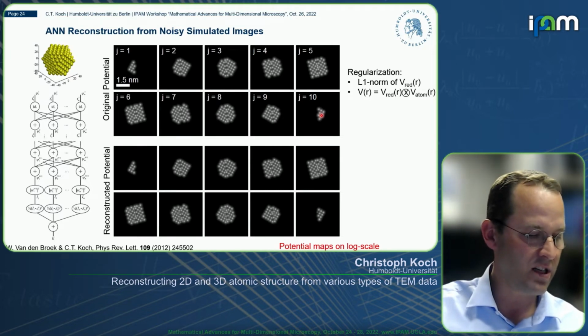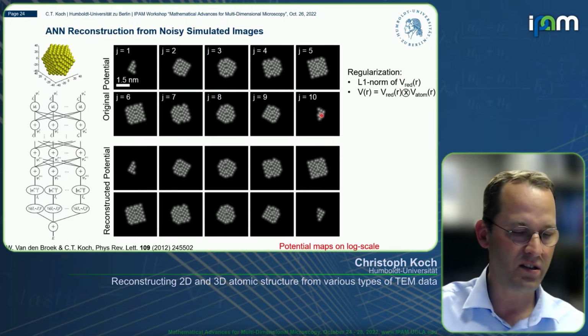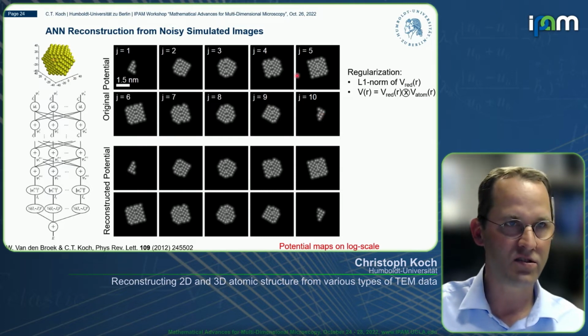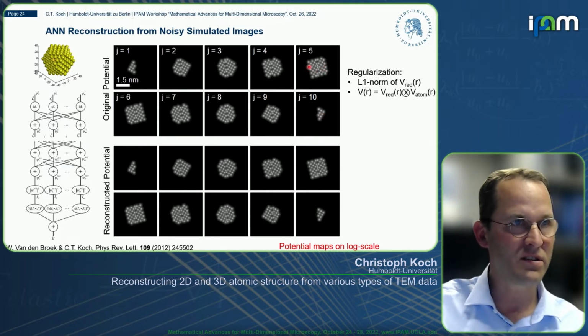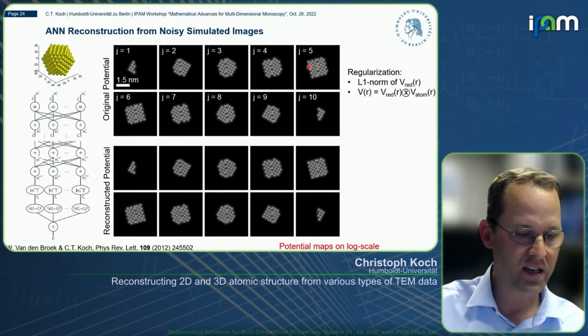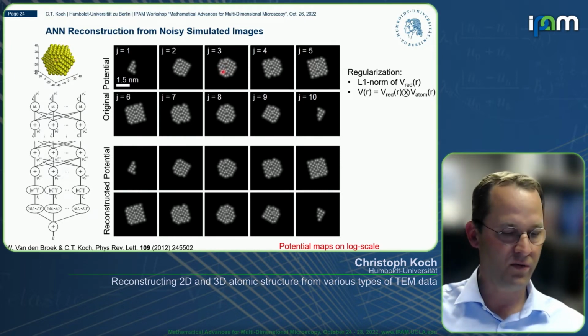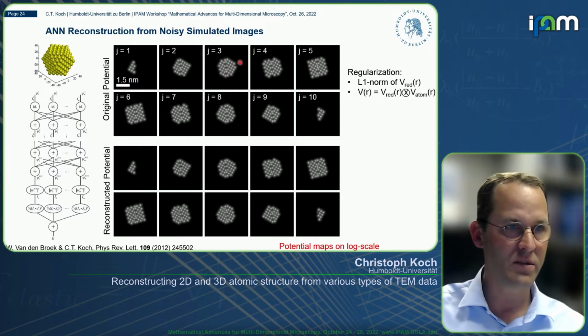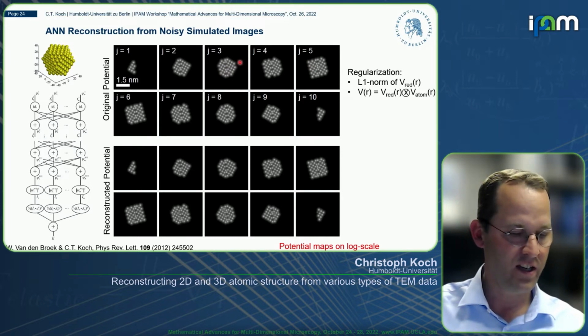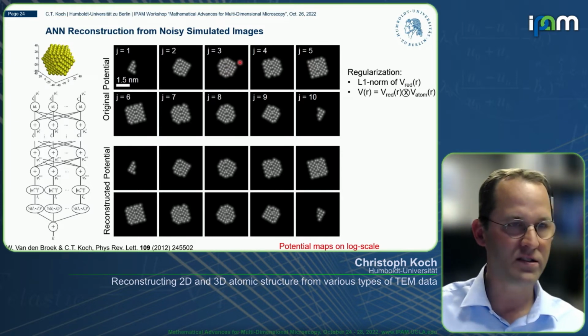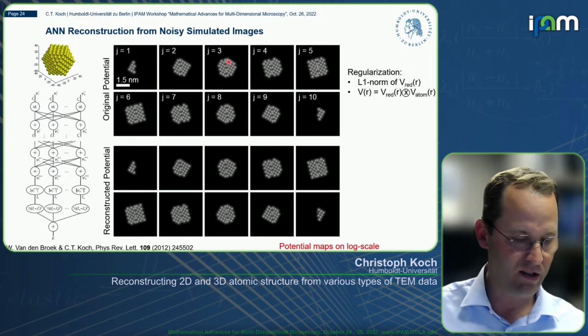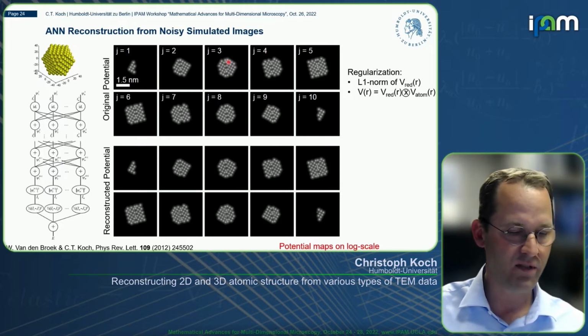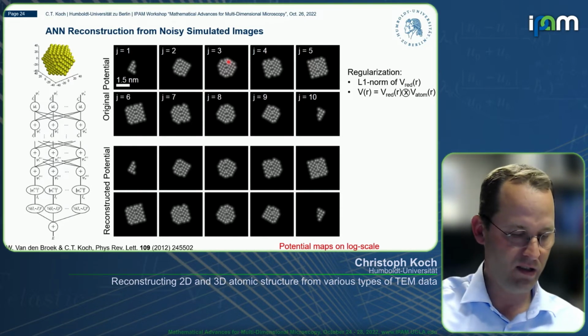And this particle here was tilted, so you can see these are not each layer is one atomic layer of the sample because they're tilted, but you can see multiple layers, for example, in this case, multiple layers of this structure here correspond to a single layer of potential, which of course makes sense. You do still have limited resolution along the Z direction. That's why you don't see them fading in and out so nicely, but you can still, from these maps, recover the position of all the atoms in 3D space.